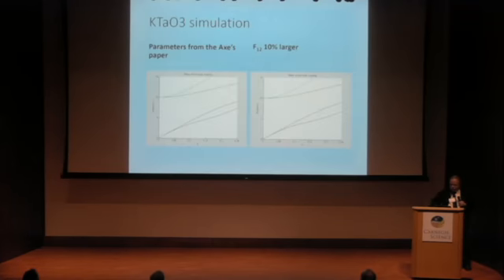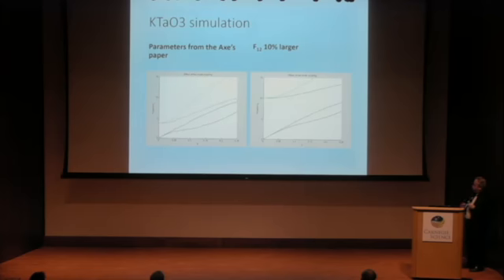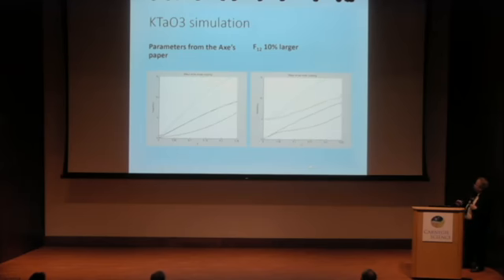Now let's use this model and demonstrate how it should develop. There are two possibilities. Let's say these are exactly the parameters that were taken from the paper of Axe and Shirane. You see the mode at the gamma point softens and softens and softens. And finally, there is nothing, because it's a quantum paraelectric. Let's use the same parameters, and let me change the parameter F12 describing the mode coupling by just 10%. You see, instead of a picture with the expected phase transition at the gamma point, we got the phase transition at some arbitrary Q. So that's indeed what can happen.